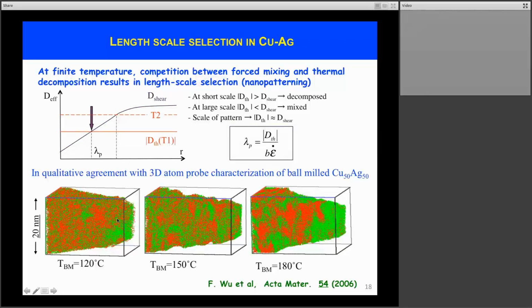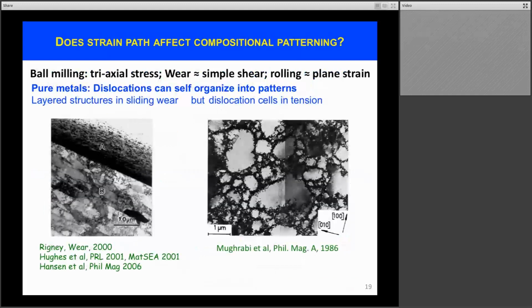And we tested this experimentally, and that's what you see in the bottom, where we have microstructures in 3D here of copper and silver powders that have been ball milled at slightly increasing temperature. And you can see that progressively in these steady state microstructures, we see increased phase separation and also an increase in the length scale of the phase separation.